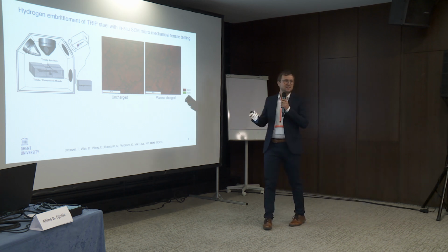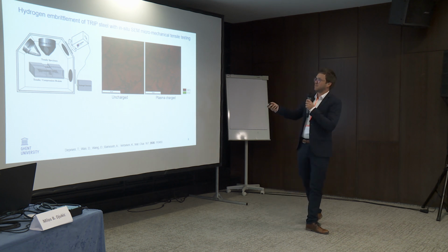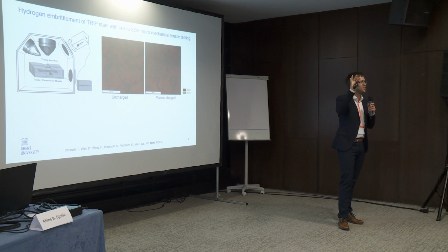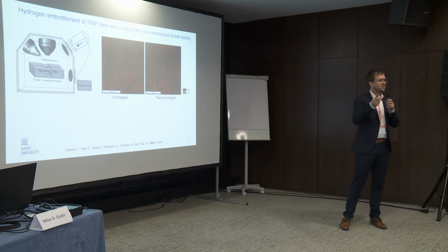To prove that this is linked to the retained austenite, I also took that sample at 20% of strain. I take it out, I go to TDS to take a look at that high temperature peak. Remember, because there we have some interaction with retained austenite and hydrogen.